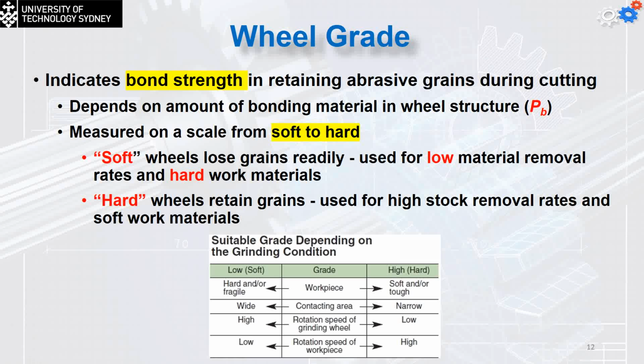So depending on this scale, from low to high or from soft to hard, depending on the workpiece, the low type is going to do the hard and the fragile materials. The high type is going to do the soft and the tough materials. For the contact area, usually the low type is going to have wider contact. The high type is going to have a narrow contact. The rotation speed of the grinding wheel is going to be high in the case of the low type and lower in the case of the hard types. And the rotation speed of the workpiece itself is going to be low in the case of the low type and high in the case of the hard type.